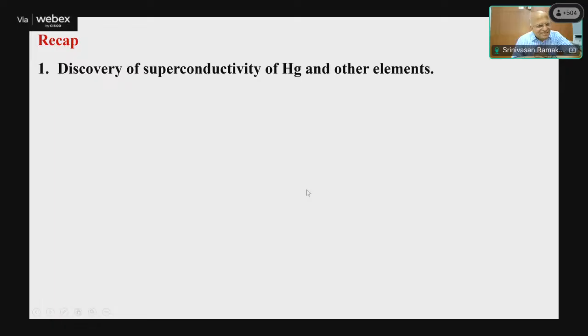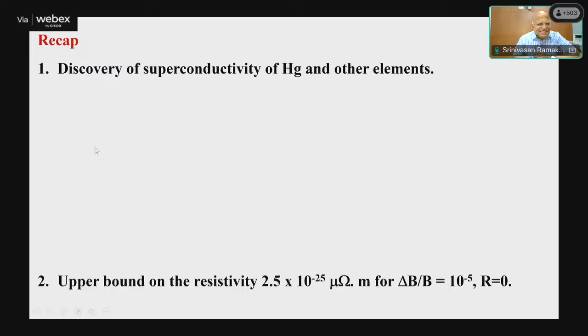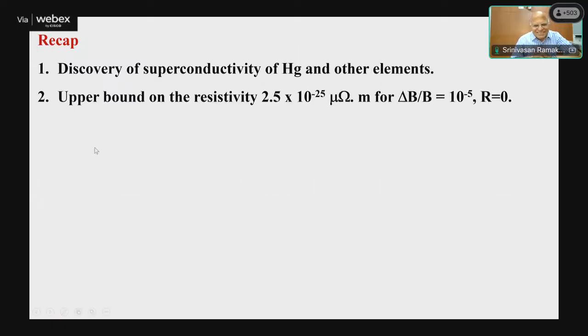Okay, so let me just give you a recap of what we have discussed. We discussed the discovery of superconductivity of mercury and other elements. Then we said the upper bound for resistivity is 2.5 into 10 to the minus 25 microohm meter. That is basically because even this limit is skimming, because we can't measure more than 10 ppm accuracy of the field. So if you measure the field better than that, this value will still go down. So for all practical purposes, we take superconductivity as resistance zero.